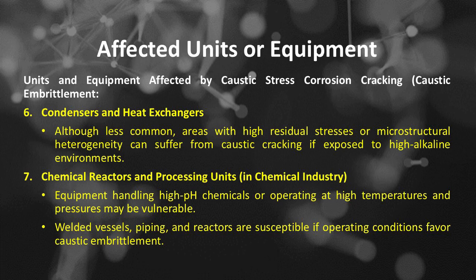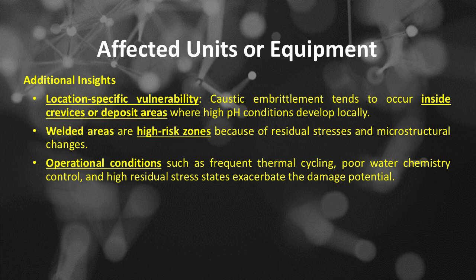Number 7 of units and equipment affected by caustic embrittlement is chemical reactors and processing units. In the chemical industry, equipment handling high pH chemicals or operating at high temperatures and pressures may be vulnerable. Welded vessels, piping, and reactors are susceptible if operating conditions favor caustic embrittlement. Additional insights of caustic stress corrosion cracking, or caustic embrittlement. Location-specific vulnerability: caustic embrittlement tends to occur inside crevices or deposit areas where high pH conditions develop locally. Welded areas are high-risk zones because of residual stresses and microstructural changes.